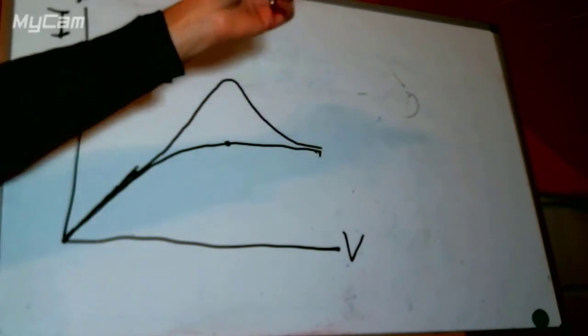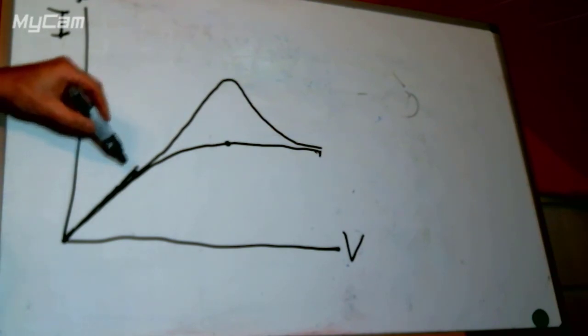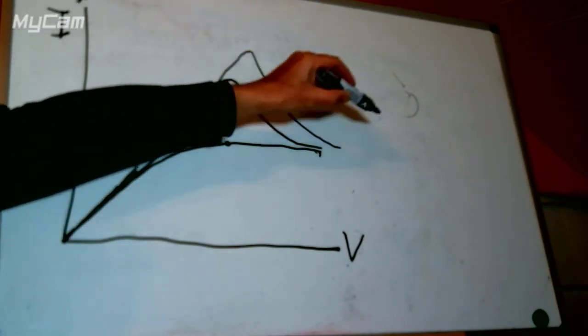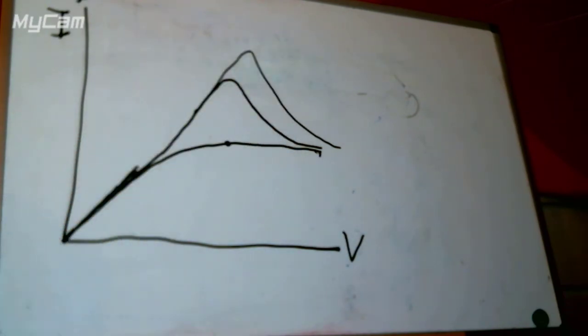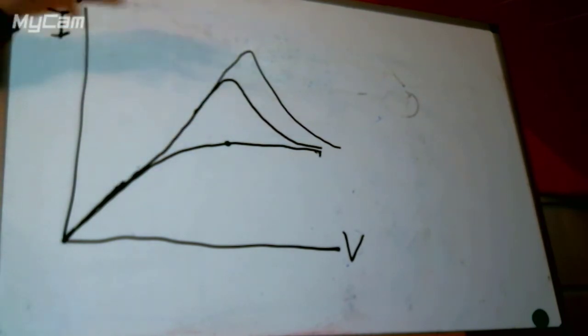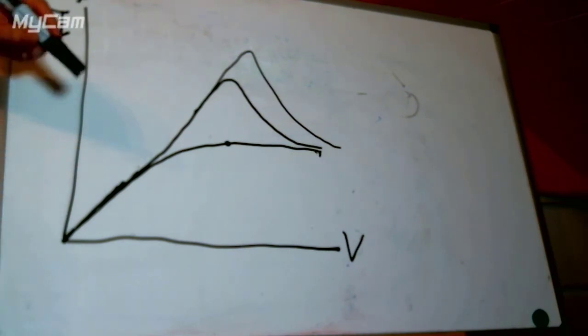The lines are the same if we go far enough. If we sweep it faster, we will get the same, but higher. We overshoot the voltage slightly more. This tells us that we're in this interesting space between thermodynamics and kinetics, where we've got kinetic effects and thermodynamic effects causing us to see things at the same time. That's complicated enough for today, so we will stop there.